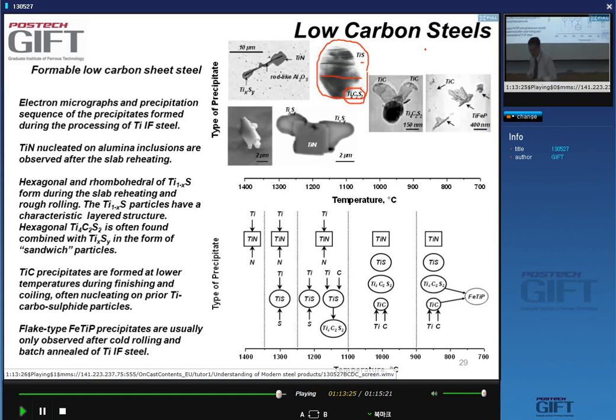It's not the only strange thing that happens in titanium IF steels. Titanium IF steels obviously are ideally designed for processing in a continuous annealing line. But because they're so robust, you can also process them in a batch annealing furnace. There's nothing wrong with doing that. However, if you do that and your steel contains phosphorus, usually very small amounts, the titanium carbide and the phosphorus may give rise to a compound, FeTiP, and it can be made either from the carbosulfide or the regular titanium carbide.